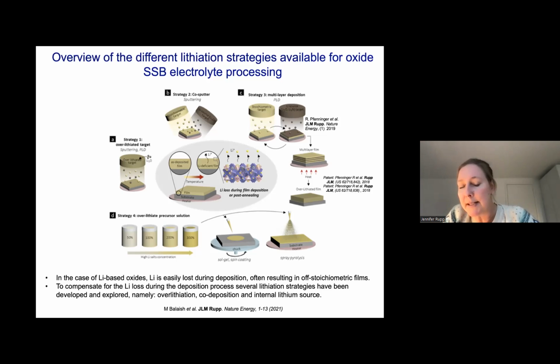The problem is that lithium is a very volatile material, so you lose it very easily, and the likelihood of losing it is quite high. So all kinds of tricks have been developed to bring it into a powder that you control, and then later to densify it in sintering to get a tape or pellet.